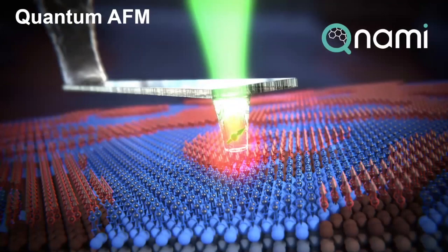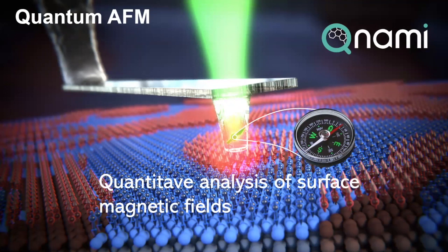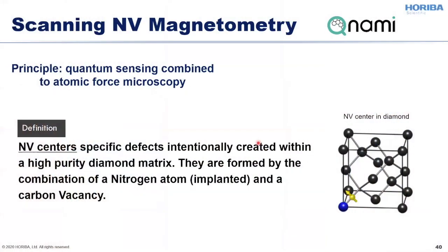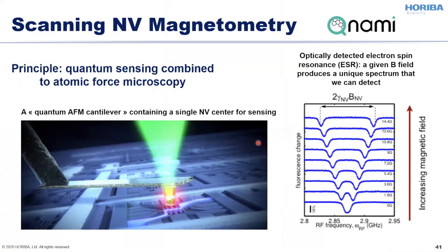Okay, and in the final part of my presentation, I would like to tell you about the exciting product from our partner company, Qnami. And this instrument is designed for nitrogen vacancy-based magnetometry. So the idea of this technique is the following. If we create in the diamond a so-called nitrogen vacancy, when one atom of carbon is replaced with a nitrogen atom, this vacancy has a photoluminescence response. First of all, it's very bright, and it strongly depends on the magnetic field in the vicinity of this vacancy.